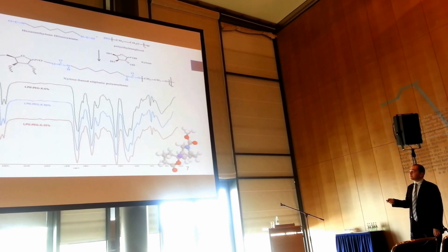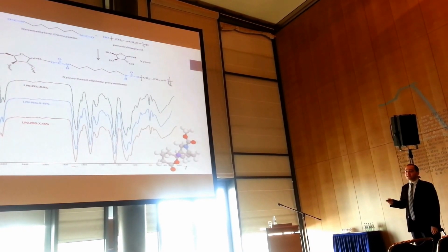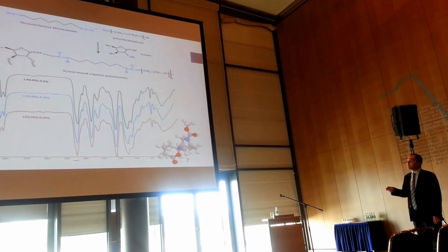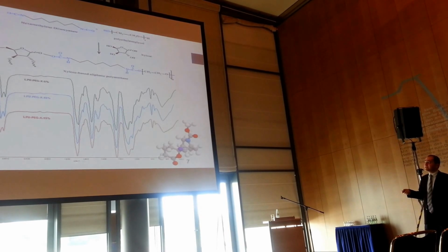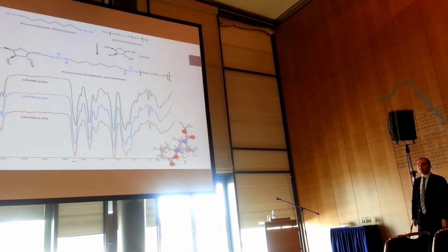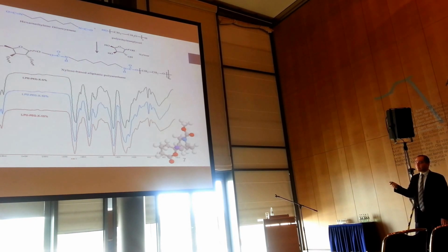And also you can check these two reverse peaks here. It's approximately 2,900. This is coming from the CH stretching of the synthesized polyurethane, and this is coming from the 3,300 peak, the reverse peak coming from the N-H vibrations, so that all of these three indicators show us that we successfully synthesized our aliphatic polyurethane.